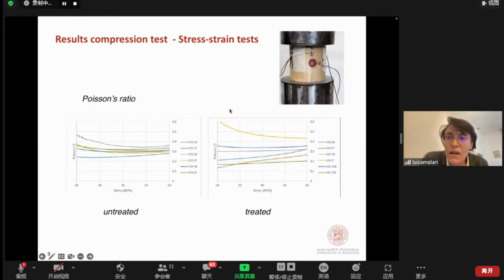the Poisson ratio. The Poisson ratio is the ratio between the circumferential and the longitudinal deformation of the specimen. And what we see is that for the untreated, we have all the specimens in a much closer range with respect to the treated samples, and this could have an explanation. I will come back to this in the following slides.